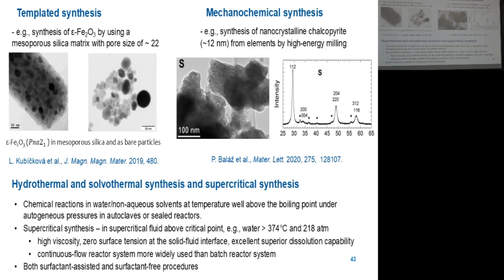I also mentioned this mechanochemical synthesis, for example, of the chalcopyrite, where you mix the starting elements, you do the high energy milling, and believe it or not, you can prepare practically single phase CuFeS2. But you can see also the morphology is not very satisfying in terms of obtaining individual particles. It is just a large nanocrystalline material which contains individual nanocrystallites, but maybe some additional mechanical processing accompanied with application of some surfactants would be necessary.